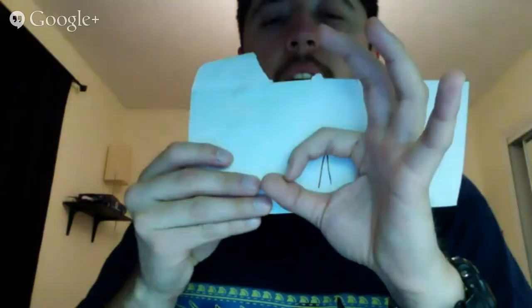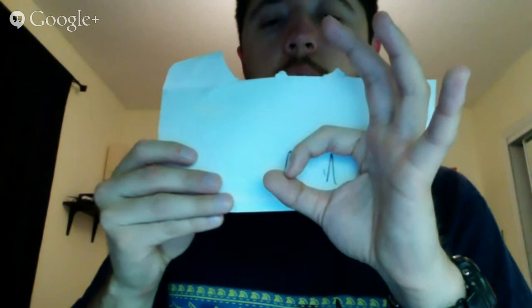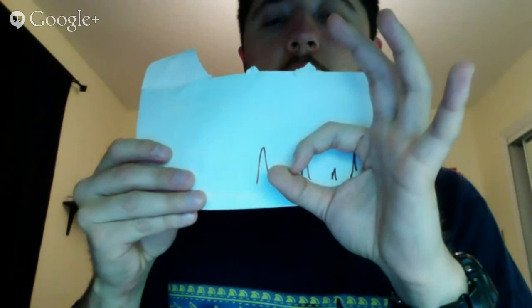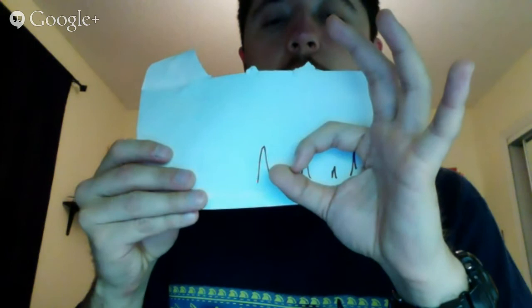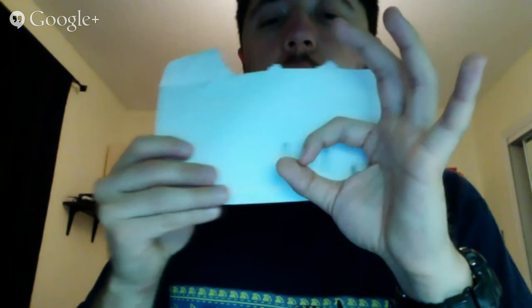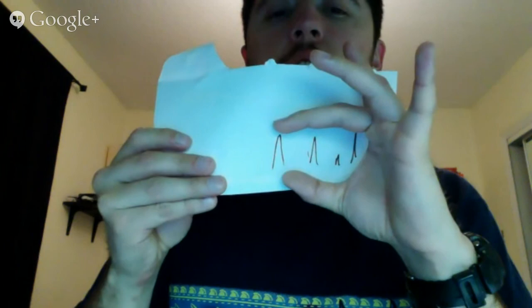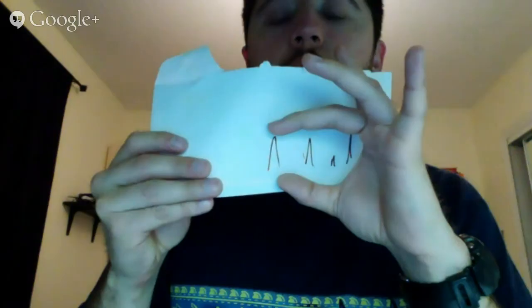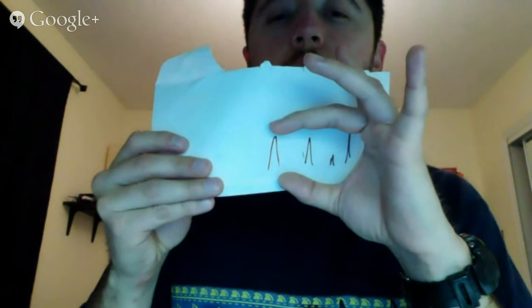What your delay does is it keeps the range the same, but it moves your screen like this. So if you're interested in having these indications at this range, you may have it like that. Now, if you're interested in looking at all four indications on your screen, then instead of moving your delay, you increase your range so your screen shows more. When you increase your range, you're putting more information on your screen. Your delay focuses your range to a smaller area.